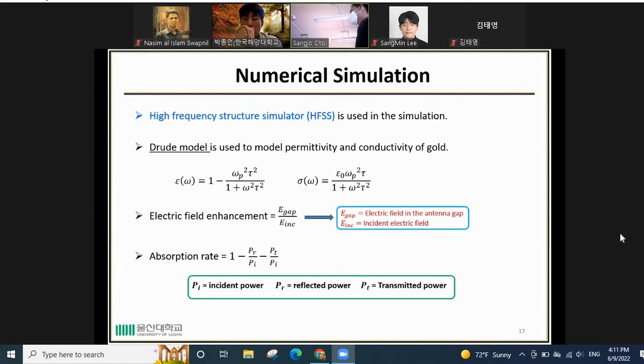Before moving to the next design, I will try to explain the numerical simulation that we use in the calculation. In our structure, we use a high frequency structure simulator for the simulation. And also the Drude model is used to model the permittivity and conductivity of gold in the infrared range. The Drude model means the permittivity and conductivity depend on the plasma frequency of the metal and also the scattering time. In our design, electric field enhancement is defined as the electric field in the antenna gap divided by the incident electric field, and the absorption rate is defined as 1 minus PR divided by PI, minus PT divided by PI. So PI is the incident power, PR is the reflected power, and PT is the transmitted power.